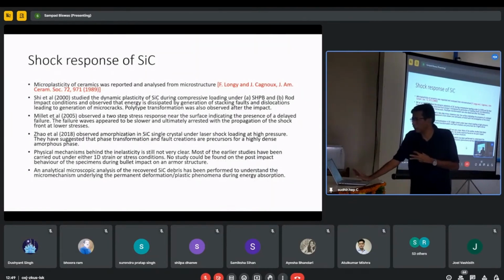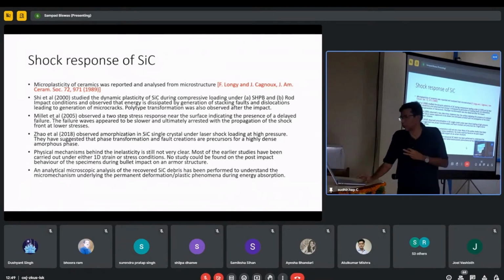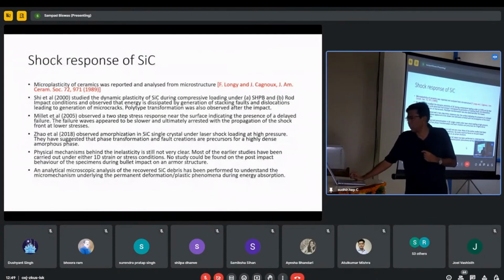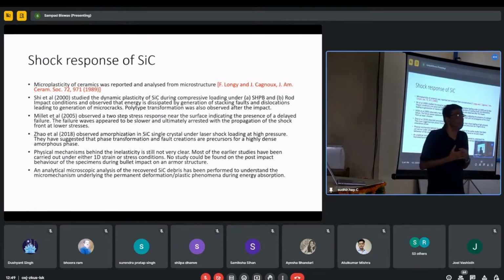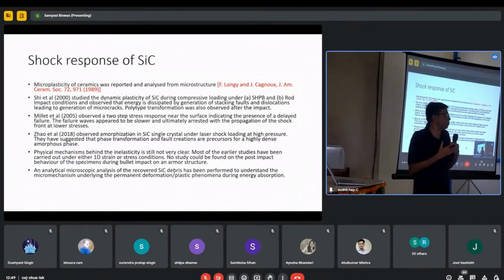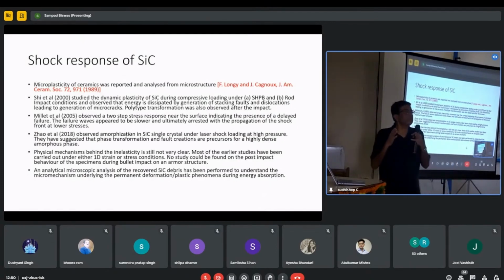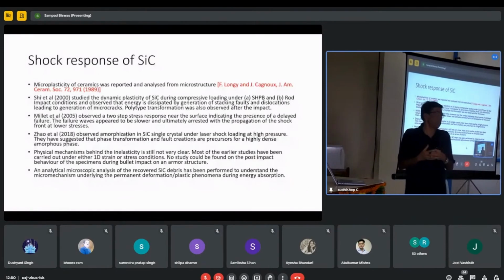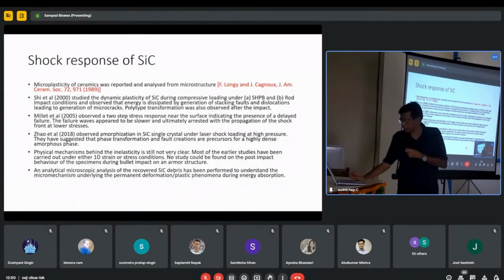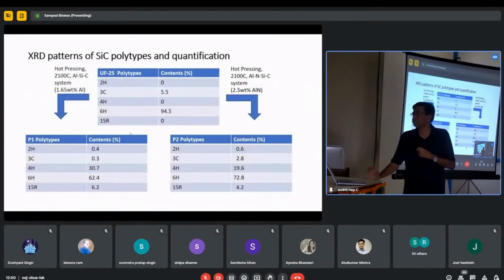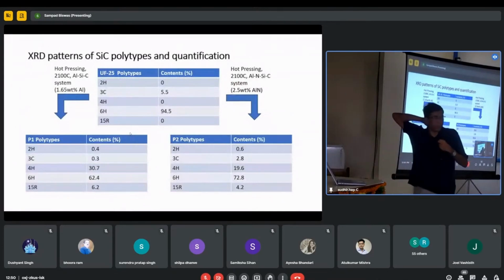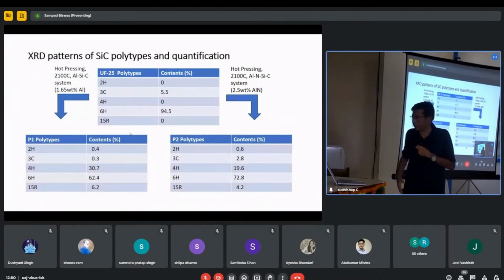So, the physical mechanisms behind the inelasticity are still not very clear. Most of the earlier studies have been carried out under 1D strain or 1D stress conditions, but in the case of actual armor, it is the multi-axial strain which plays a very important role. So we have carried out our experiments with actual hits of the bullet, recovered the spent specimen, and then carried out the further characterizations. This has not yet been done so far. We have not got any report from anywhere of anyone who has done this.